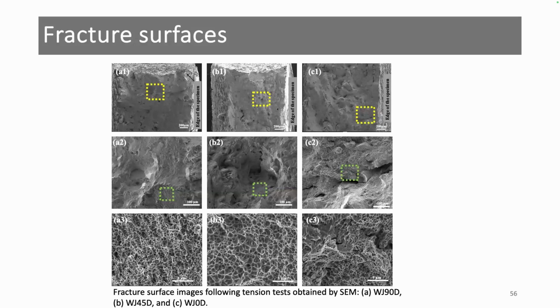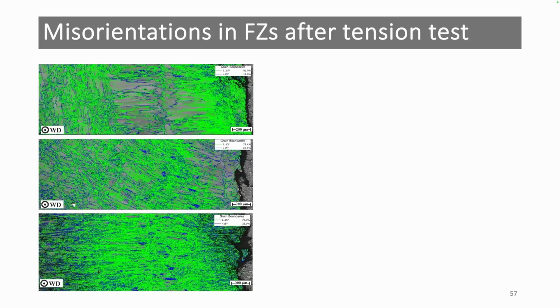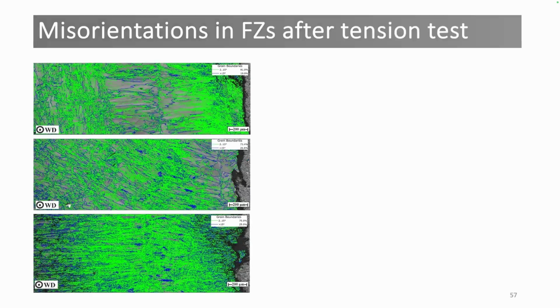Regarding the fracture surface study, we found that most of the specimen also have this type of ductile fracture. This was laser welding. And here this is still some analysis of the mechanical behavior or the microstructure behavior during the tensile testing. We are still figuring out why that this fusion zone and the 0 degree give this amount of deformation more than that of 90 and 45 degrees.